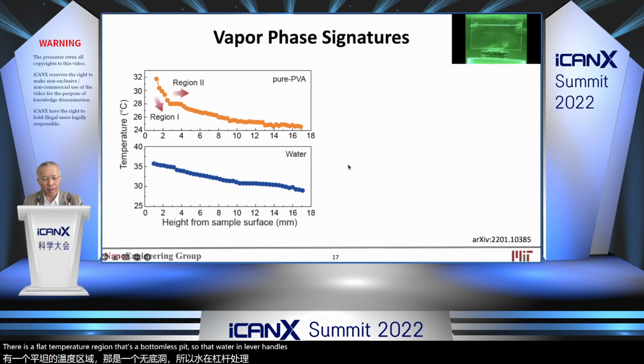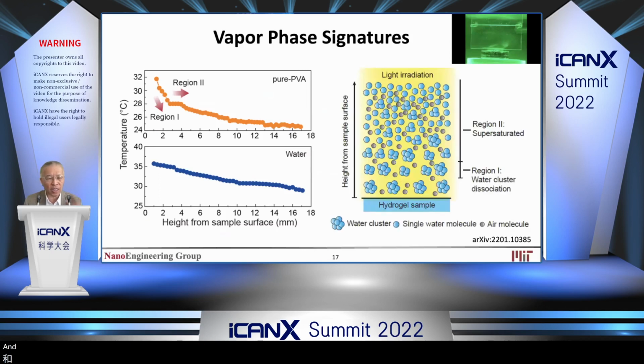And the explanation we have now is that when a photon excites the water cluster into vapor, the cluster breaks up. They actually absorb heat in the vapor phase. So they first absorb heat. That's why there is a cooling effect. And then when the vapor gets saturated, you get a flat temperature region. That's why we have a flat temperature region.